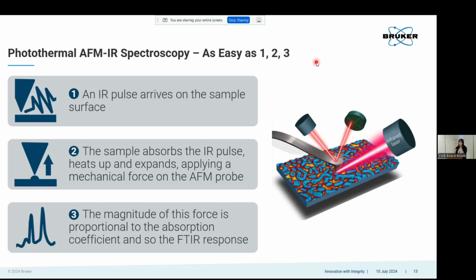And this expansion is really, really small. It's on the order of an angstrom, so like less than a nanometer, on the order of a single bond length between like a carbon and a hydrogen. Really, really small. But because we have such a sensitive force detector on the tip sample area, we measure that force being applied to the cantilever, and we can read that out. And it turns out that the amount of energy that the sample takes in is directly proportional to how big it gets when it feels one of these pulses, which is what you measure with FTIR for 50 years now.